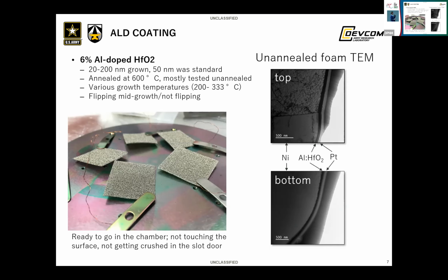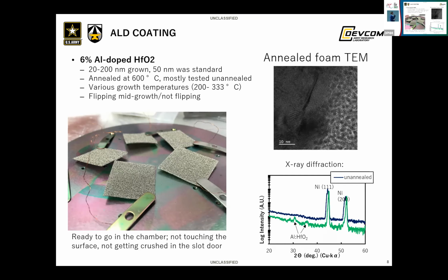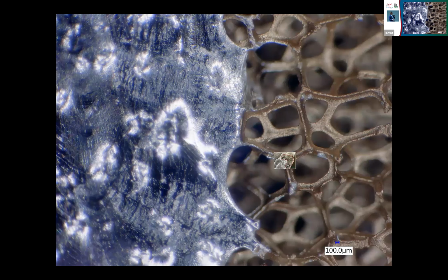Still, it grew, and so we can see some TEM of some unannealed foams, and then we were able to anneal the foams, and you can see grains here, and then there are these two little peaks that correspond to the alumina hafnia. Now, here's a photograph of the interface of what a coated infiltrated foam looks like. And if you've never played with liquid metal, it is a crazy non-intuitive substance. It's very dense, and it has this crazy surface tension. So actually getting the liquid metal to want to get into this foam was a challenge in and of itself. We did a bunch of chemical treatments, and it turned out that just pushing it as hard as we could, we even centrifuged it, was the best way to get it to infiltrate the foam.